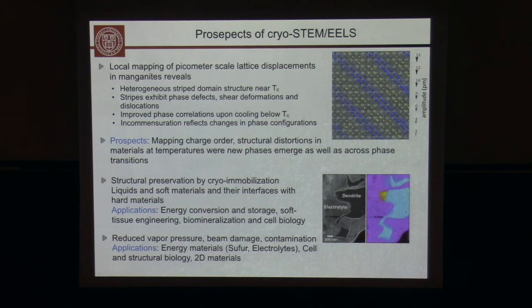So when you cool, you go below that temperature. It reduces beam damage, and that's really good for organic materials. It also reduces contamination, and so unfortunately today, our collaborators making nanoparticles sometimes can't get them clean enough for us. If you cool it down, you can give us dirty samples and we can actually produce high resolution results. So this is actually a big deal, even though it seems very small and mundane to you.